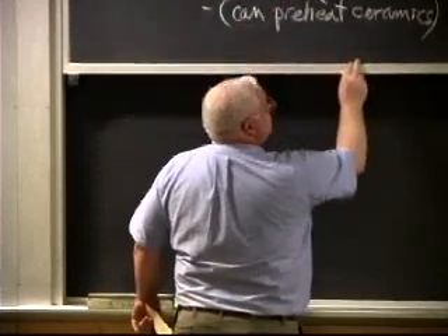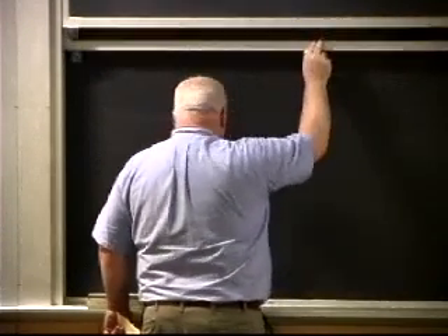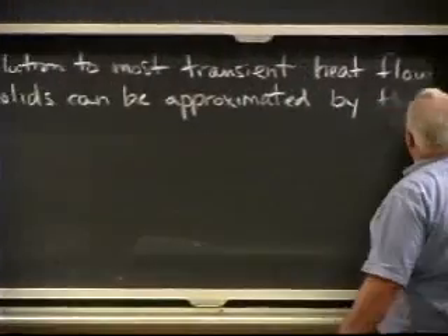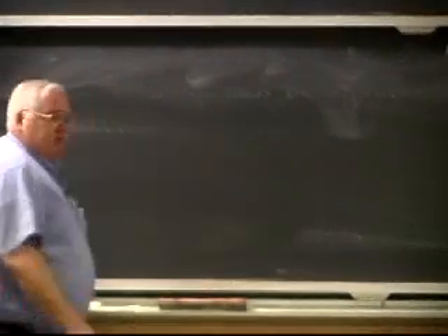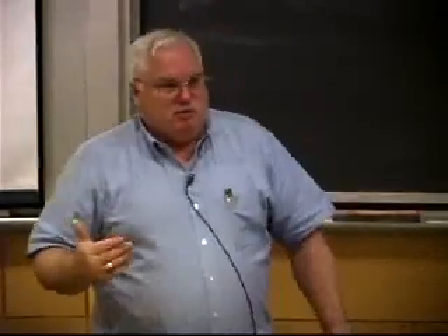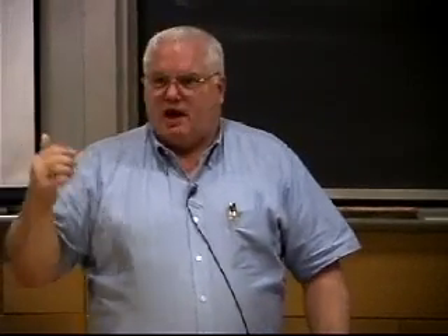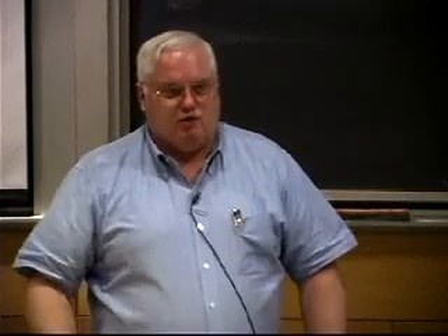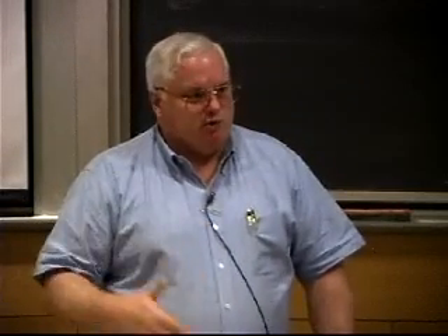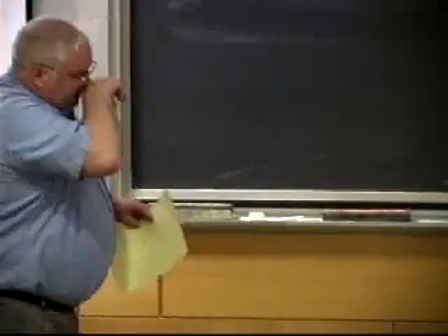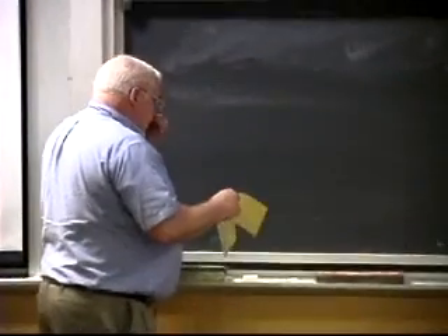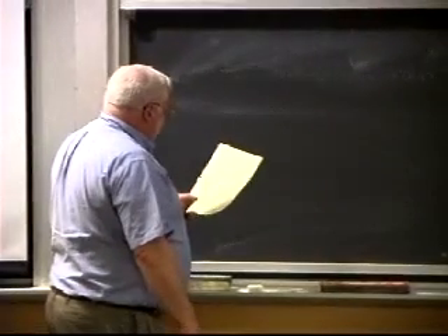There were some studies done at the Naval Research Laboratory by a ceramist, Roy Rice, who's no longer there. 15 years ago he would basically preheat ceramics to 1,000 degrees centigrade, and lo and behold, there was enough conductivity in the ceramic at the high temperatures that the electrons would be carried away, and he was able to electron beam melt. Now it turns out, just because you can electron beam melt, most of the ceramics that you electron beam melt have little cracks running right behind the pool. So it's not exactly a good welding process because it is a cutting process as well as a welding process because of the crack that forms. But he was just trying to demonstrate whether you could do it. And there are a couple of ceramics that actually don't crack, but it's kind of specialized.